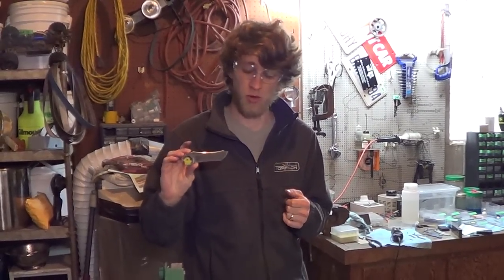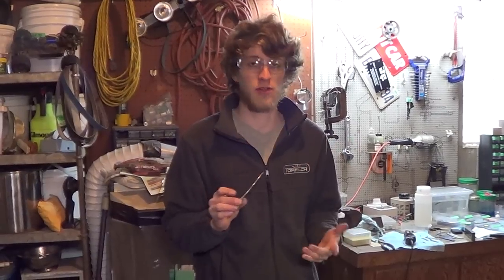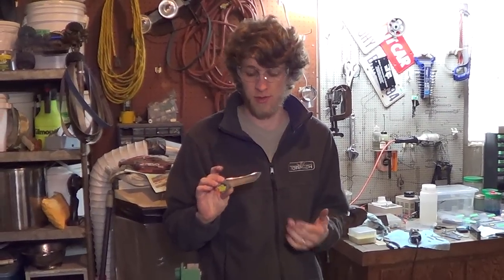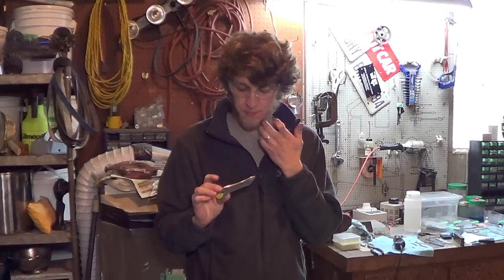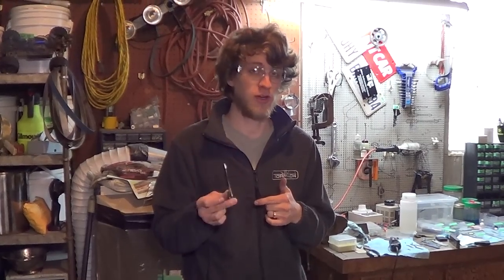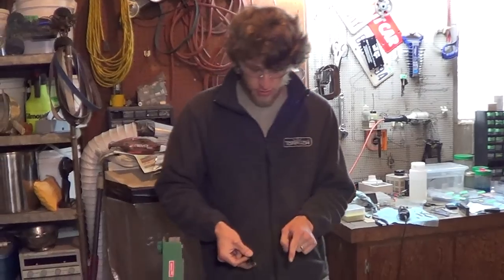I've been playing with etching damasteel more this morning and I think I got the perfect solution figured out. I googled it and apparently ferric chloride is not the best to use on damasteel because the two metals are very similar and they etch at a similar rate. So a lot of people say muriatic acid, which is what Brian Tai told me. But a lot of people in Europe also say sulfuric acid, which is battery acid.